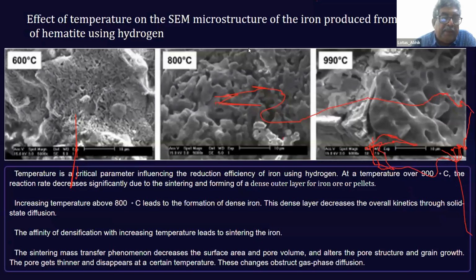I'm showing some microstructure growth when hydrogen is being used, and you see that the microstructures are of different temperatures, 600, 800, 900. Actually, this doesn't happen with carbon. With carbon, the microstructure at the 600 level to 800 level to 900 are more or less the same. That doesn't change. Okay. But if you use hydrogen, then the microstructure changes. The problem is that if you increase the temperature, I don't want to get more into it, but if you increase the temperature, then you'll find the sintering, that you will find that porosity of the iron ore reduces.